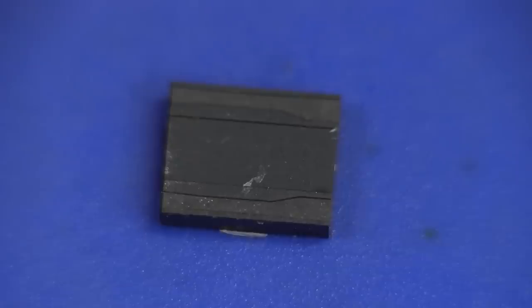Really neat design. Now, a lot of the early magnetic alloy materials used in these heads are things you've probably never heard of, like molybdenum permalloy, things like Sendust and Alfenol, go figure. But then they moved on to some more amorphous ferromagnetic alloys, and pretty much ferrites dominate the industry these days for heads, even around this era. So this is probably some form of ferrite material. And these new ferrite materials are usually either like a nickel zinc or a manganese zinc type combination alloy, but they're certainly not just your regular ferrites you'll find in your inductors and stuff like that.